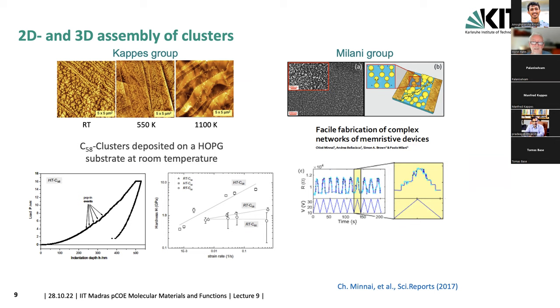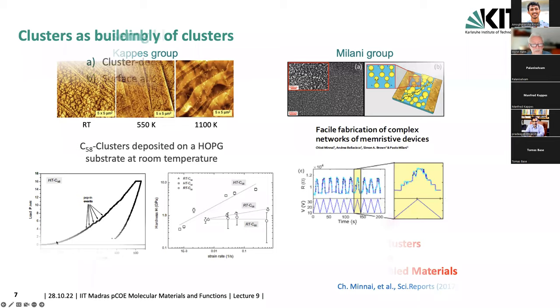And of course, one thing is from the Kappes group, and they have taken C58 clusters, consisting of 58 carbon atoms, and they have deposited them on HOPG graphite at room temperature. Because you have a large amount of these clusters available, you can grow fairly thick films and study their properties. What you see here is, for example, a nano indentation: the indentation depth versus the load. The load increases with increasing indentation depth, and then you release it and you end up with plastic deformation.